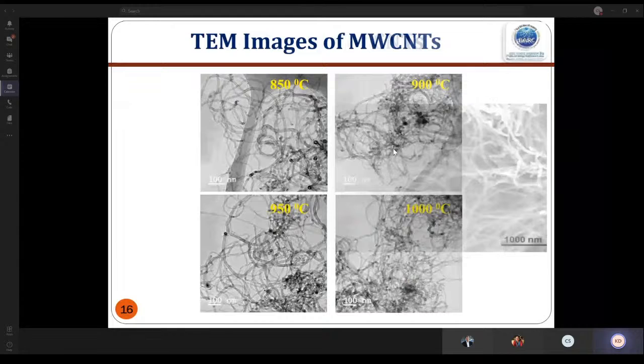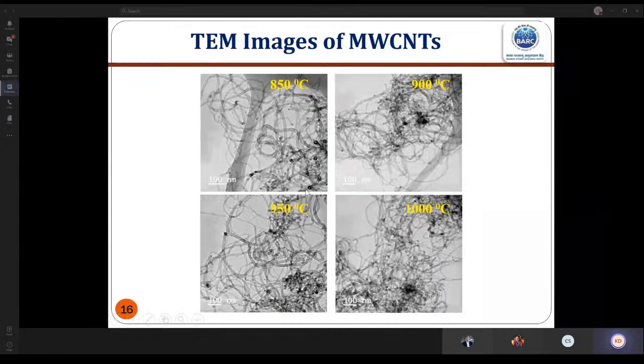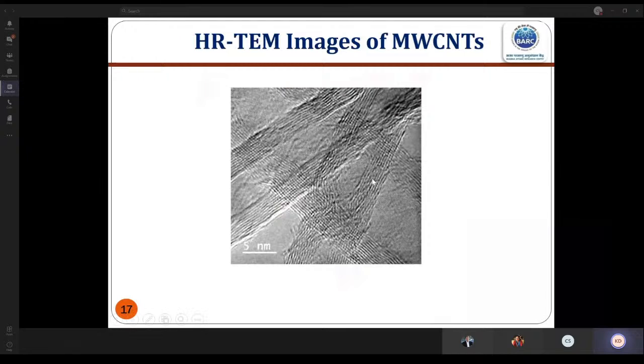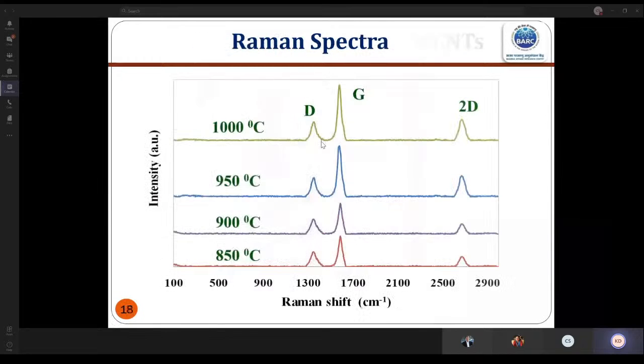After that, we can go for the TEM, that is the transmission electron microscope, where we can see the detailed structure. Okay, inside is hollow, so we can call it carbon nanotube. We can go for further high resolution, that is called high resolution TEM. Here I can count the number of walls also. There may be 8 to 13 walls, and this is the outer diameter, this to this is the inner diameter. The inner is hollow, and these are the walls. We call them multi-wall, because we can count more than one wall. So this is a multi-wall carbon nanotube.